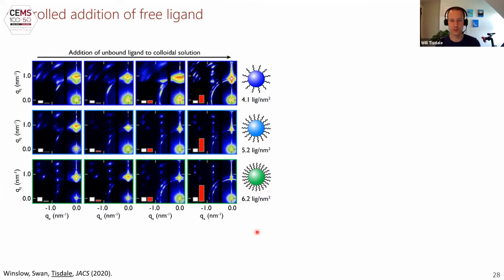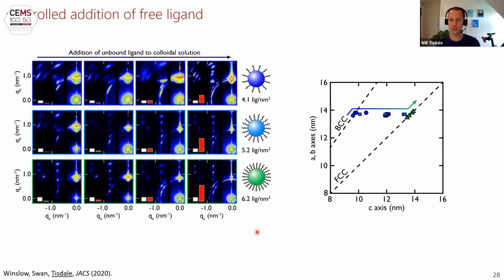You're not supposed to be able to learn much from looking at those patterns. What's more interesting is if you look over here on the right. So for the very under-coordinated samples, they tend to form BCC structures. And as you add more ligand to the surface, they push into this body-centered tetragonal phase. If you start with a very heavily coated nanocrystal surface, it starts as FCC and then stays as FCC as you add ligand, but the lattice constant just gets larger and larger.